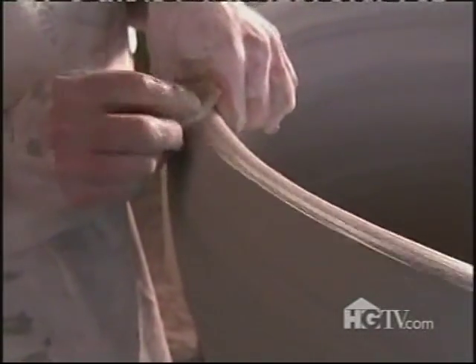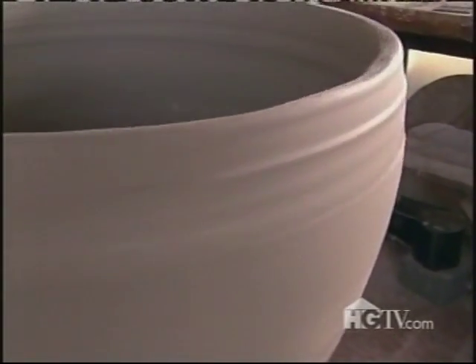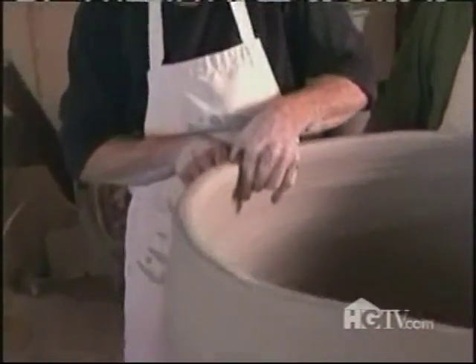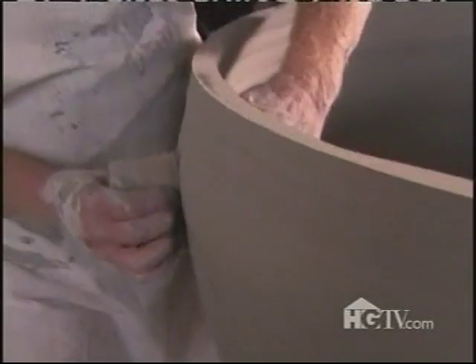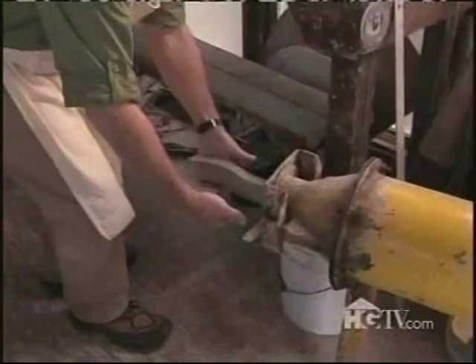And we're going up. We've got to take the lump somewhere, so we're taking them up to the top. As you come up to the top, you press down. This coil will give the pot another five inches of lift. The uneven lip is again trimmed to leave it nice and level for the next layer. Next, we'll take out this wooden rib and smooth it down. Sometimes you want the texture, but we're going to do this in a nice, shiny glaze, so we want it to be nice and smooth. From here, we again let it spin dry for an hour, score the lip, apply the slip, then extrude another coil.